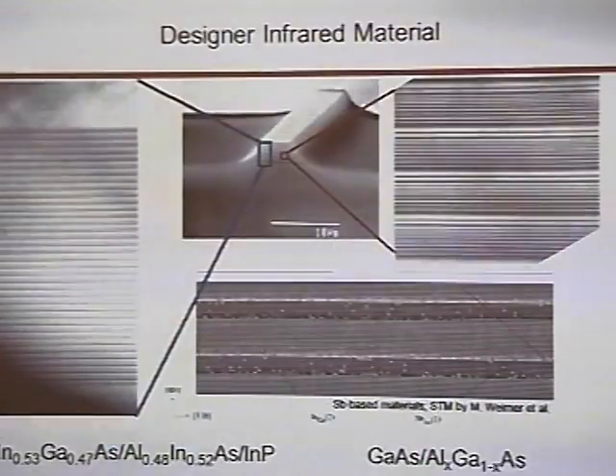So when I moved to Harvard, I decided I'm going to team up with a big company then working on telecom lasers, Agilent Technologies, to demonstrate that we could make quantum cascade lasers using vapor phase epitaxy. So we succeeded, and this has been quite important, because the reason there's been this rush of many companies making quantum cascade lasers is you can now use the same equipment, the same techniques used for optoelectronics at telecommunication wavelengths, using the same materials of telecommunication wavelengths, but in a different wavelength region, which is the mid-IR, because you are not using the actual band gap. So the band gap doesn't matter what it is, but it helps that you use materials that are state-of-the-art for another wavelength region. So this, I claim, is one of the key reasons for the growing commercial penetration.